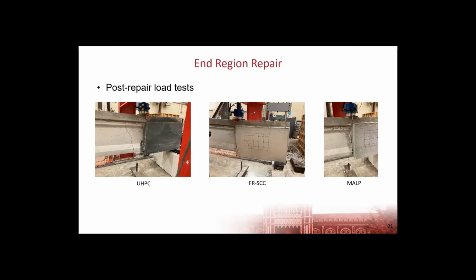You have to remember that there is cracking underneath the repair that was already there. But in each case, we primarily saw new cracks outside of the repair. In all cases, those cracks actually extended past the load point in terms of shear cracks, which was a little bit unexpected. For the FR-SCC and the MALP concrete, we did see a crack right at the interface between the repair and the beam. And then, for all three repairs, we saw very little cracking actually in the repair material. We saw just a few cracks in the UHPC and FR-SCC repairs. We didn't see any in the MALP concrete for either specimen we tested.